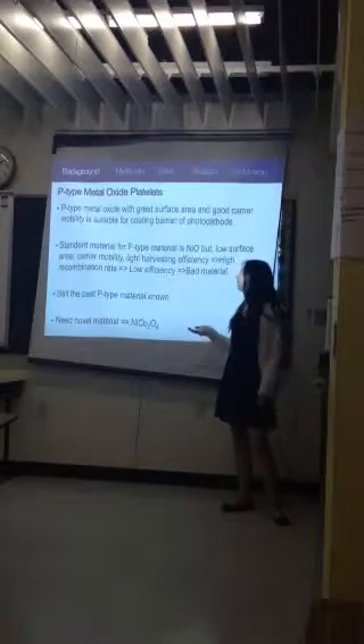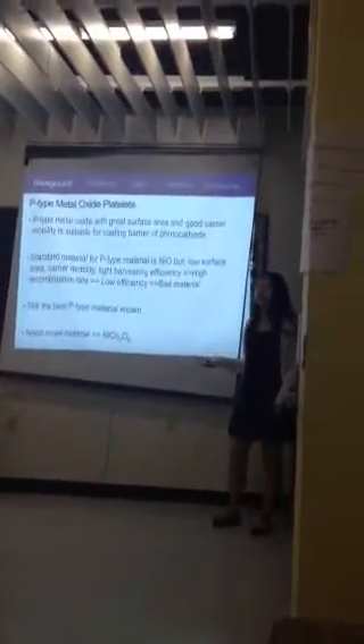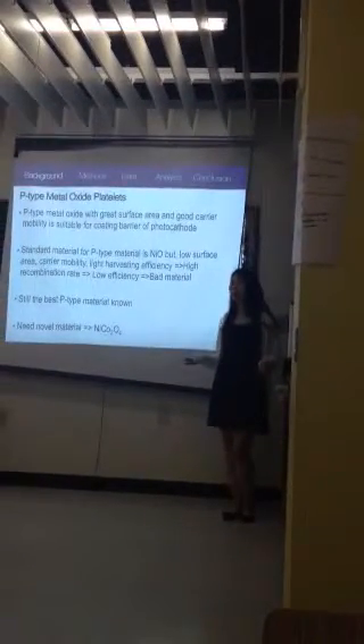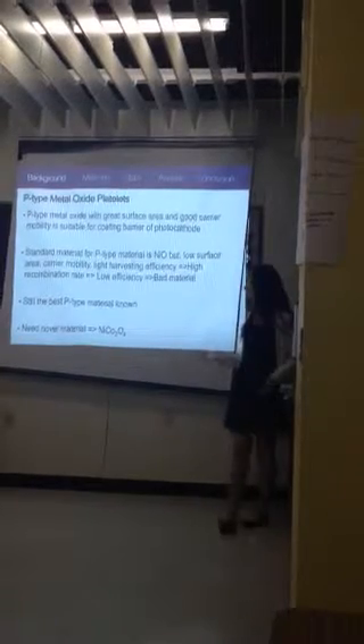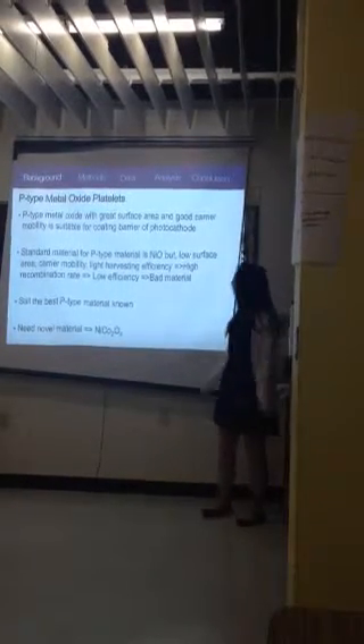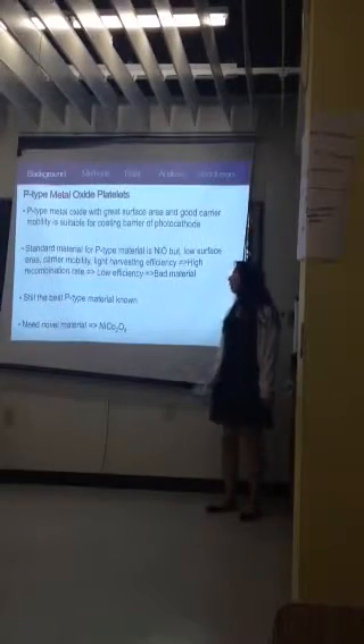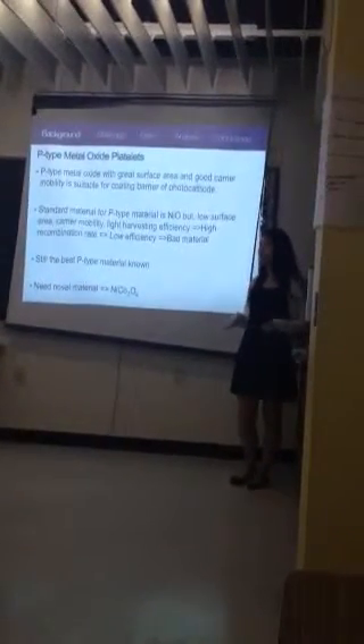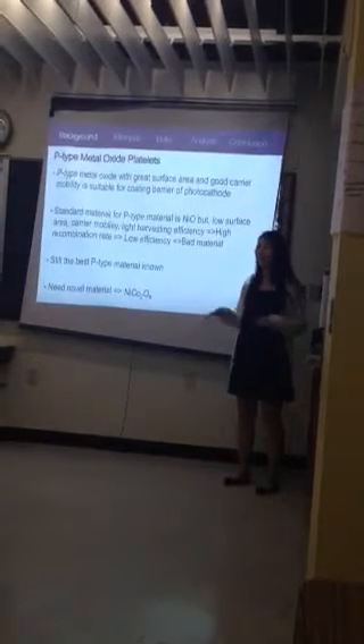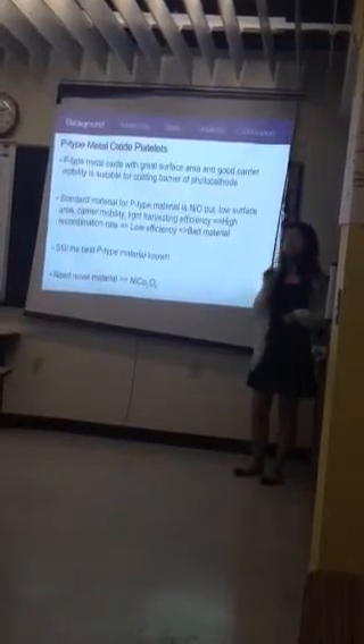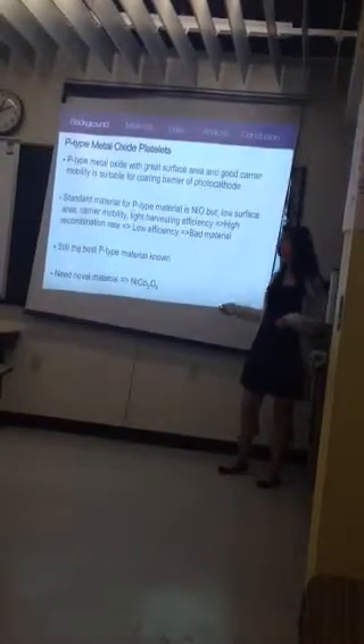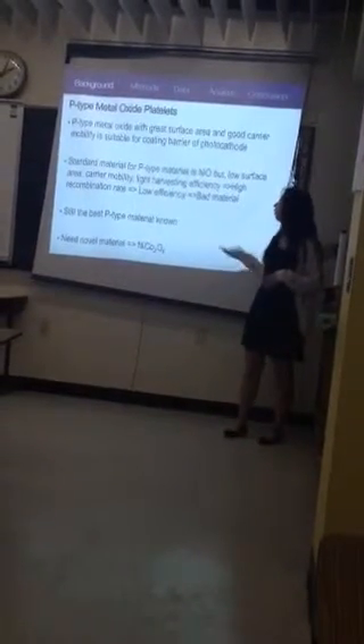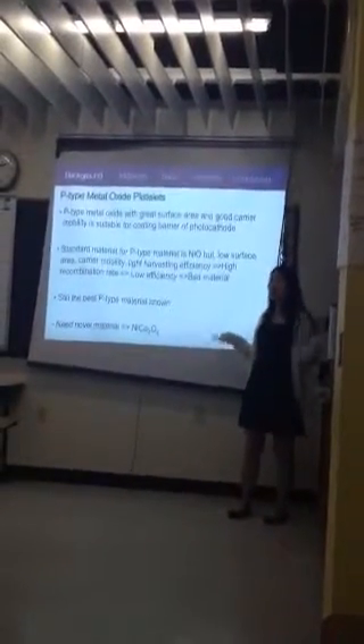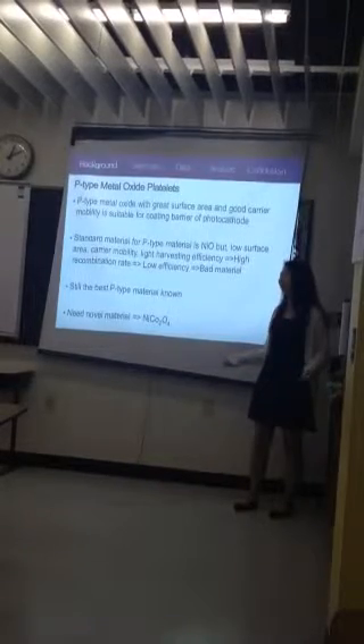The standard material for this P-type material these days is nickel oxide, due to its best performance so far among all the materials used. But it's not the best material, for a lot of reasons. First, it has very low surface area, and terrible carrier mobility, which limits the film thickness coated on top of FTO, and leads to low loading of dyes and very low current production. All these traits also lead to a very high recombination rate. Therefore, this whole system is very inefficient. So this is not a very good material.